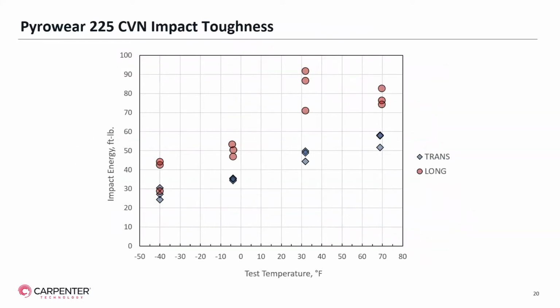We've looked at ductile to brittle transition temperature behavior of Pyrowear 225, both in the longitudinal and in the transverse orientations. This image shows both. The red dots are in the longitudinal orientation and the blue diamonds are in transverse. The takeaway here is that even at very cold test temperatures of minus 40 degrees Fahrenheit, we're still in the mid to upper 20s in terms of impact energy, and that's in the transverse orientation.